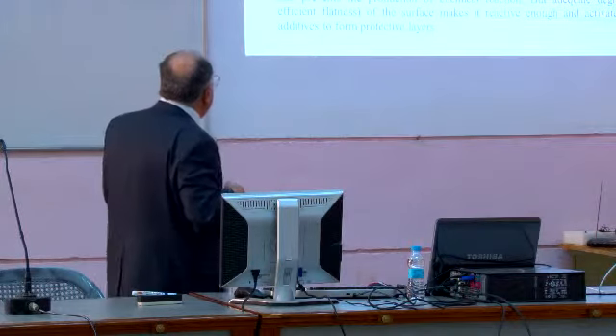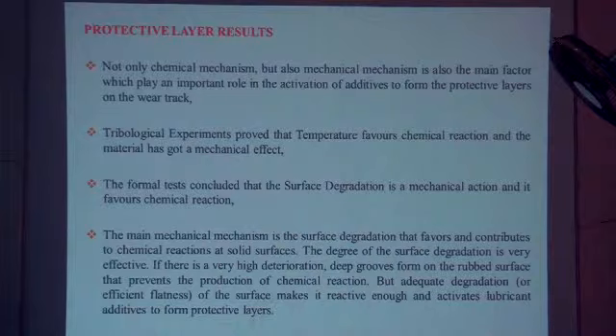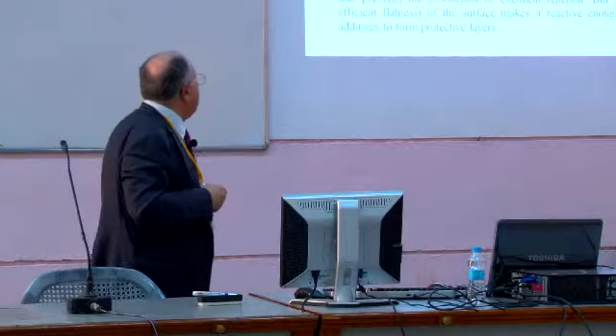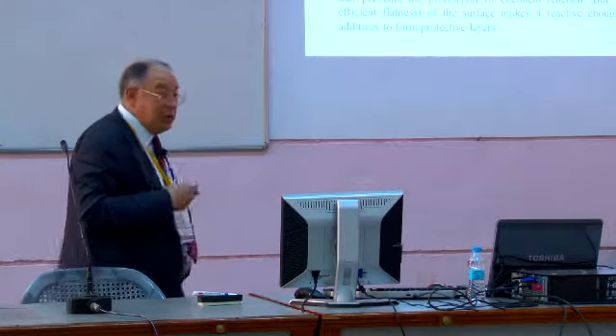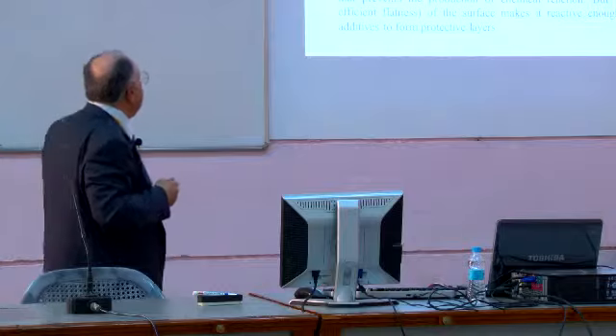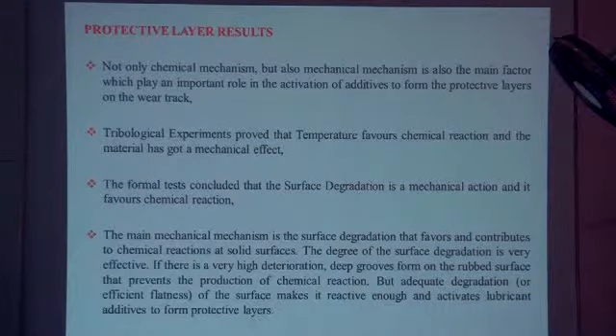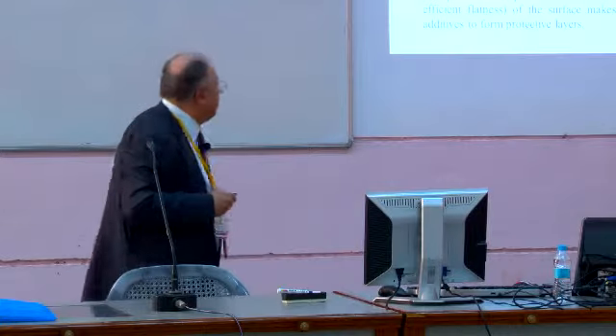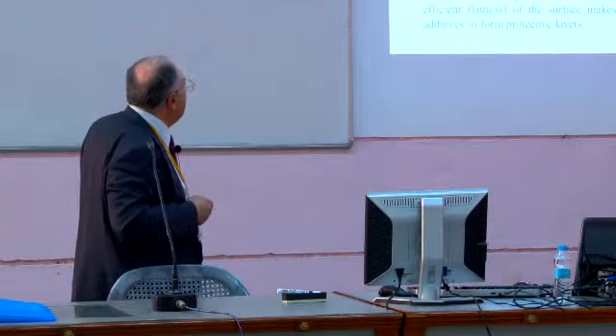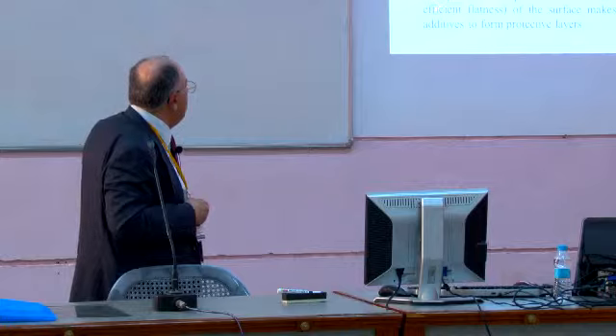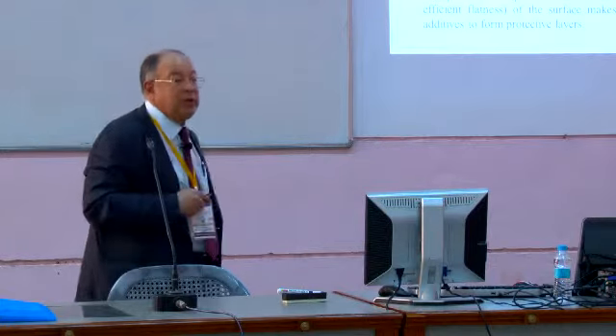Well, what is the main mechanical mechanism? It is surface degradation, as I told you, which favors and contributes to the chemical reaction on the surface. The degree of surface degradation is very effective. If there is very high deterioration, if the surface is much more degraded, or there is scuffing in a dry test, is the material gone? Is it still possible to get additive layers on the surface? Because deep grooves form on the surface and prevent the chemical reaction.